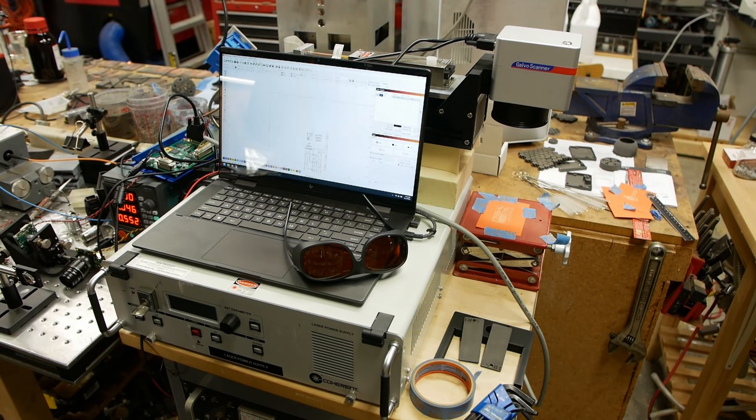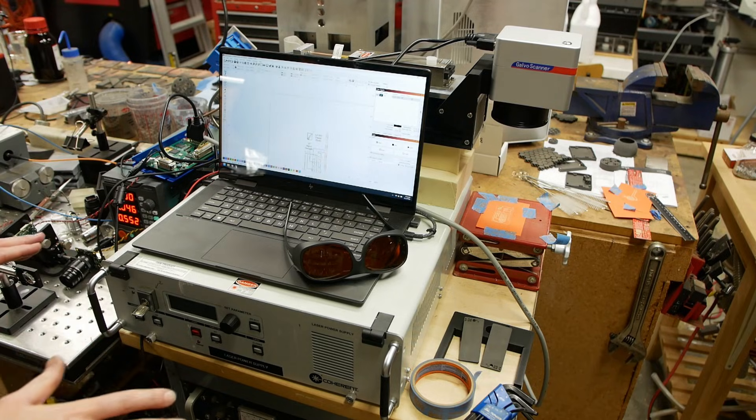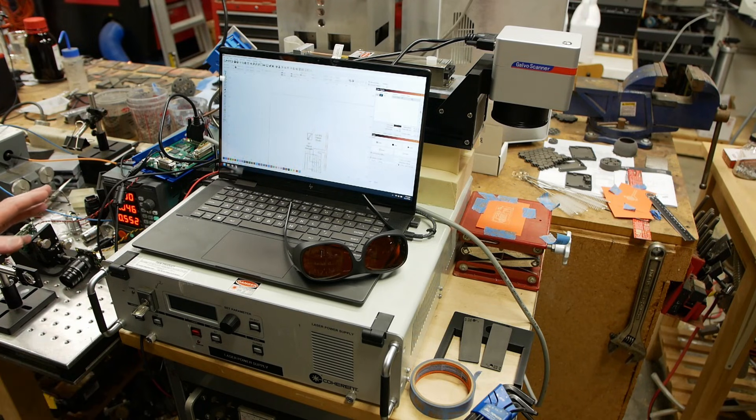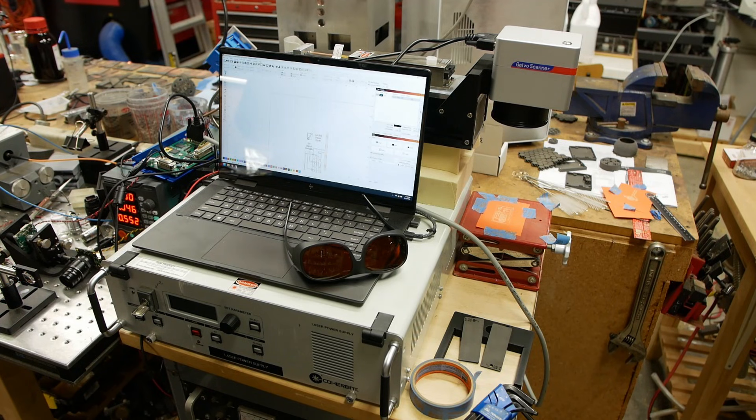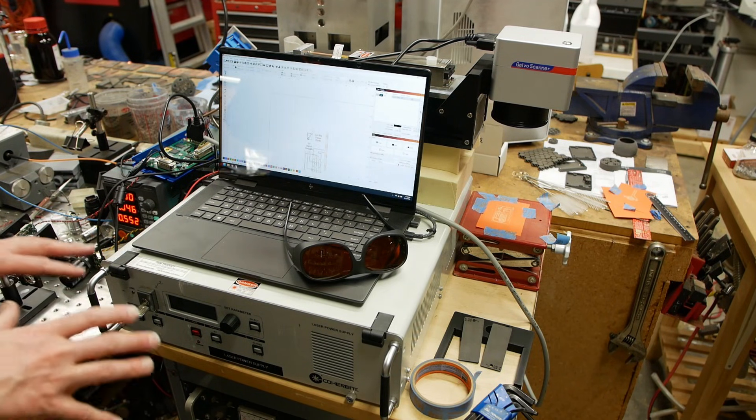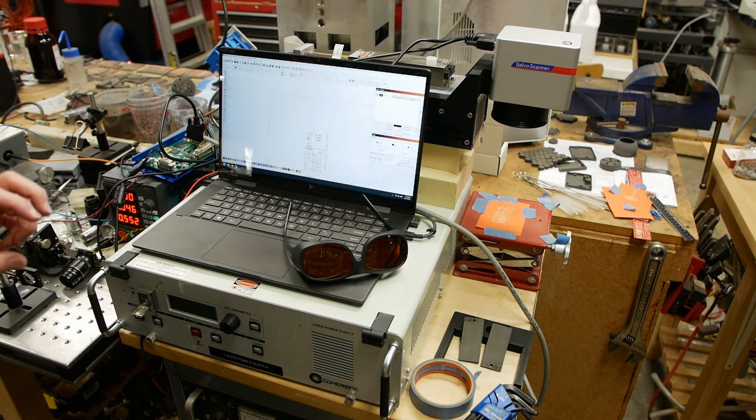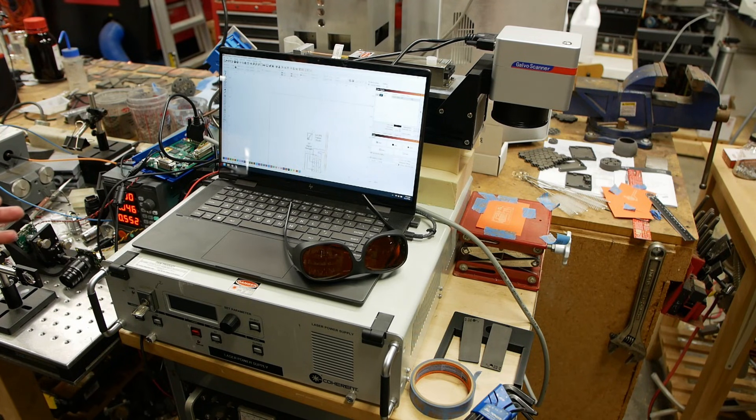Once the part is cleaned and dried, it's ready for laser exposure. And this is my laser setup. It's not a typical 1064 nanometer scanning laser that you might get on AliExpress, for example. This was more or less donated to me, and it is a green laser, much rarer, but actually more difficult to use in this context because all of the parts out there are built for 1064 nanometer lasers. And this is a frequency doubled 532 green laser. It's also only one watt, but it's still pulsed. And that's really what matters for this catalyst activation. Another lucky thing is that the catalyst absorbs light across the spectrum. So it doesn't really matter if you pulse it at 532 or 1064 nanometers, as long as you get the energy into the particle in that pulse, it will become activated.